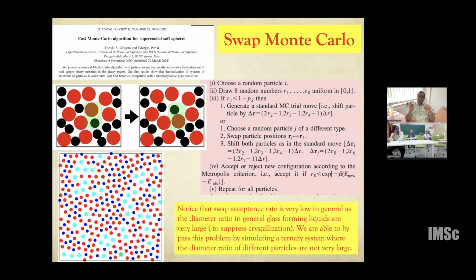And one can easily see the difficulty. In a dense environment, a smaller particle can easily be placed in the position of a bigger particle. But the bigger particle cannot be put in the place of a small particle because it is going to overlap with the other particles, so this will be energetically very costly. That's why these moves will be very, very rare. If you are dealing with binary mixtures, the acceptance rate sometimes goes to 10 to the minus 5 or 6. But surprisingly, even with that small acceptance rate, the dynamics can be sped up significantly.